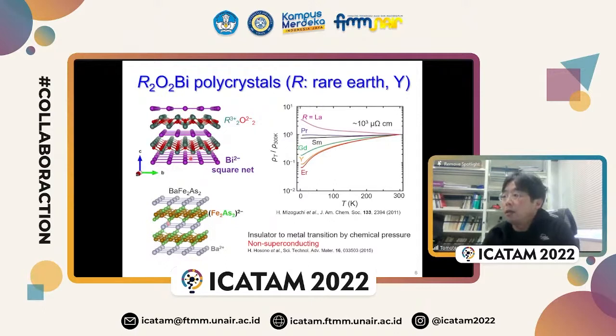And about this compound, previously Professor Hosono's group reported that this compound is electrically conducting. If the rare earth is small, the bismuth bond length is shorter and the interlayer spacing is shorter. In this case, the resistivity decreases with temperature, so this is metallic conduction. By changing the rare earth, for example to the largest, lanthanum, this becomes an insulator like this. So by changing the type of rare earth element, we can control the electrical conduction. In other words, this is a chemical pressure by changing the rare earth elements.